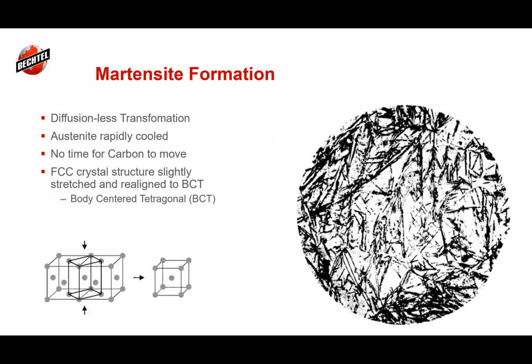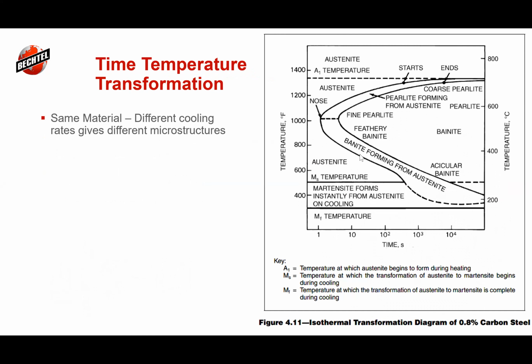Okay, so some of the basics that I wanted to cover are the microstructure, and how we really use the phase diagrams, and the things that we do are the time temperature transformation diagrams. So this one here is done for a relatively high carbon steel. It's a 0.8 carbon steel, but it gives a good example. On the vertical axis, we've got temperature, and we have time. So now we start talking about what we're really interested in, which is cooling rates, and how long it takes to cool down.